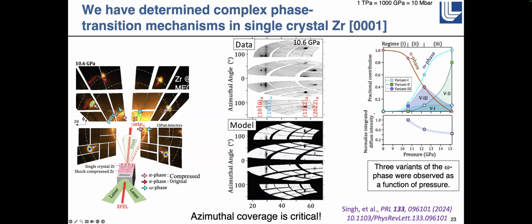And what was really surprising, as we went up in pressure, we saw three different variants of the omega phase that involve different orientational relationships, different ways that the atoms are moving around for the same orientation. As we move through it, the amount of signal that we got in each variant was different. We initially saw variant 3 and variant 1, and then variant 1 remained constant, variant 3 started to fall off, and variant 2 started to overtake.